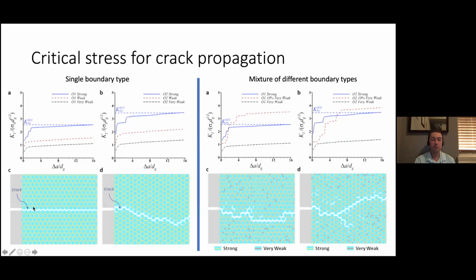To give you a very simple perspective on what happens, here is a crack that runs through orientation number 1, when all of the grain boundaries are exactly the same type. So let's say they're all equally strong, and the crack is oriented for easy propagation along the interfaces between these grains. This solid very easily undergoes intergranular fracture. If you look at orientation 2, which is what I'm showing here, the crack now takes a somewhat more tortuous path. It's harder for it to go from the left to the right, basically because this particular orientation is not as conducive for a very straight crack to run directly across. So you see a little bit more tortuosity, a little bit more deflection, but overall it's just a single crack that runs from left to right, okay?